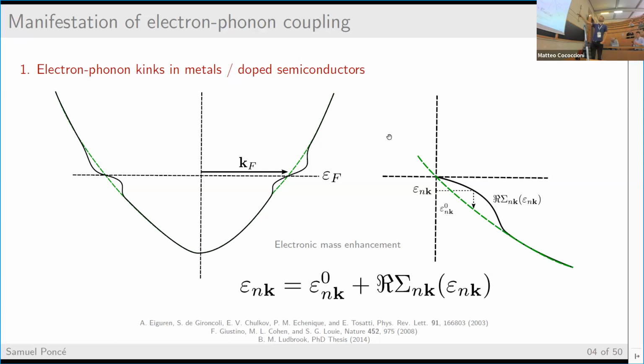One of them is that in metals or heavily doped semiconductors, you have the emergence of kinks. You can really see them in ARPES experiments, in which you have a small kink close to the Fermi level. If you know the bare dispersion, and there are different ways, you can simply use a parabolic model, or you can do a DFT calculation that doesn't include the coupling between the phonons and the electrons. This is your bare dispersion. By definition, the measured dispersion is equal to the bare one plus the real part of the electron-phonon self-energy. So by looking at this kink and measuring these differences, you can extract or reconstruct what the electron-phonon coupling is.